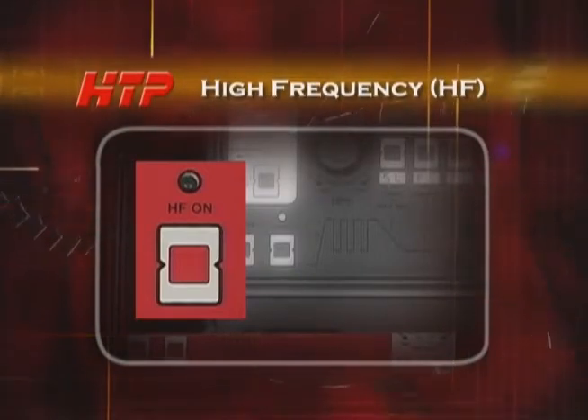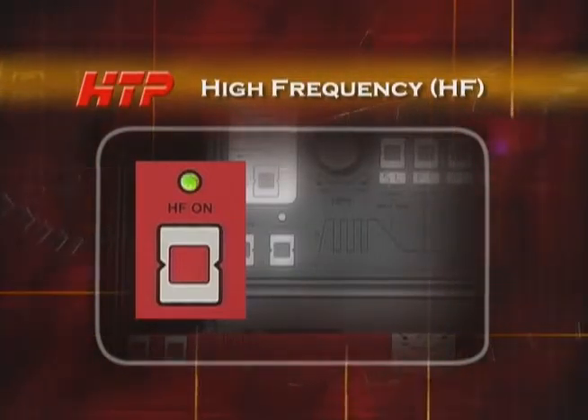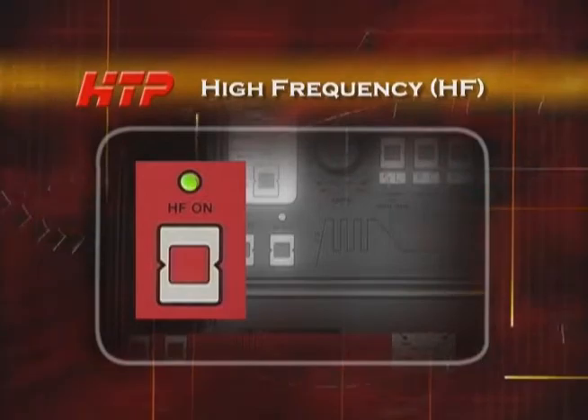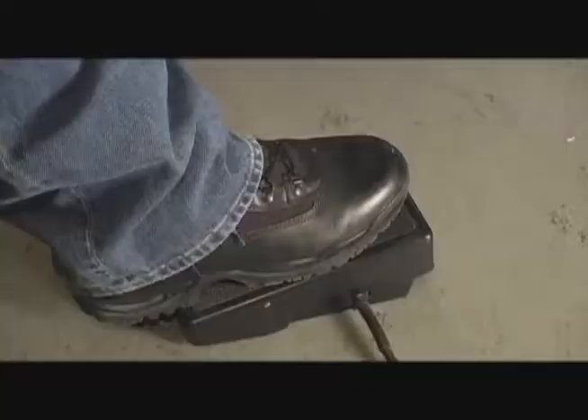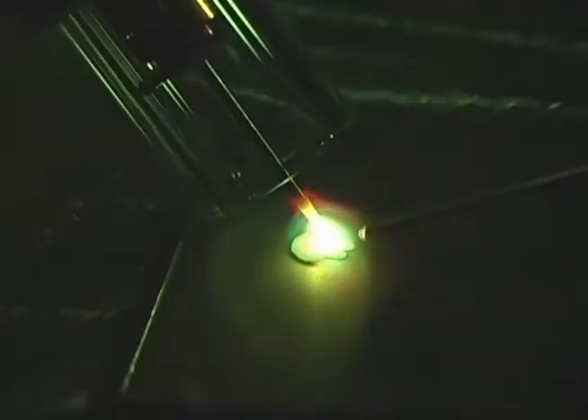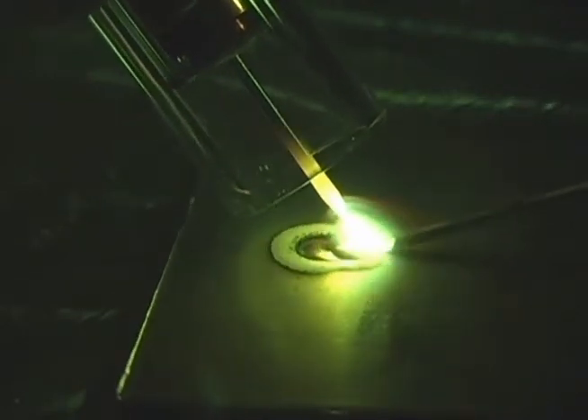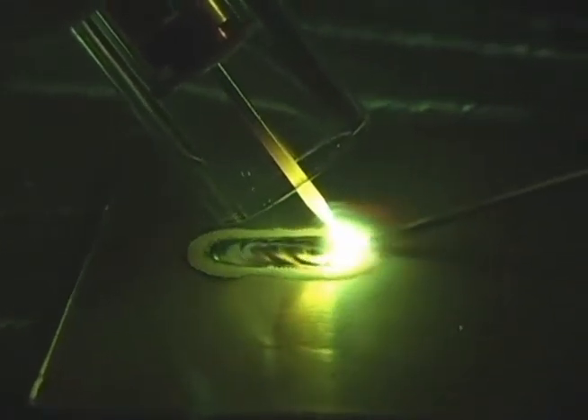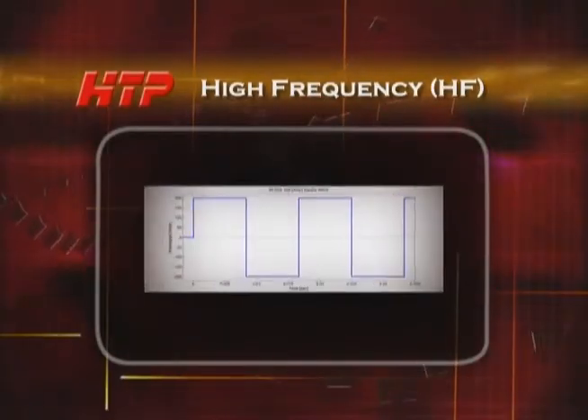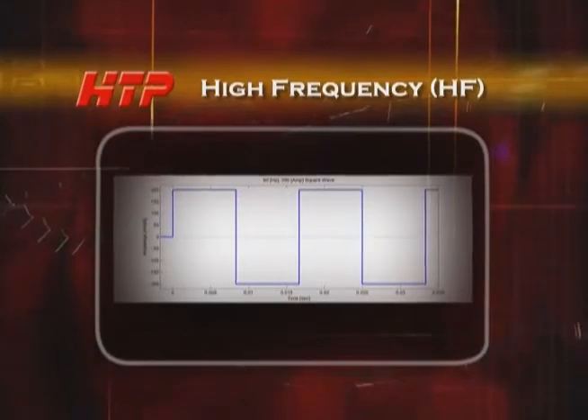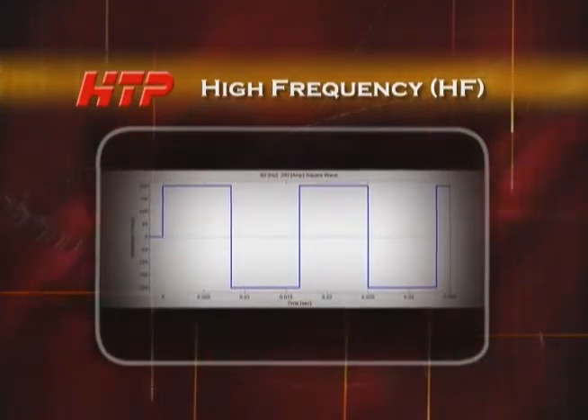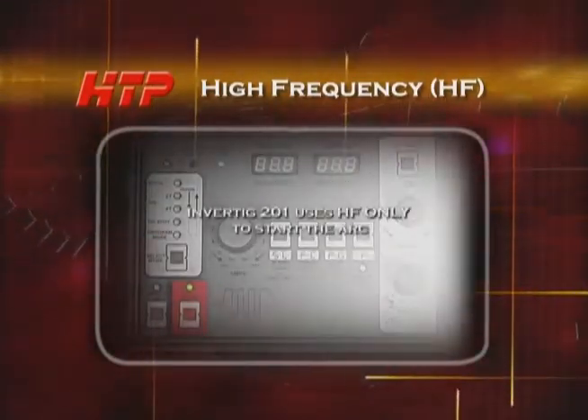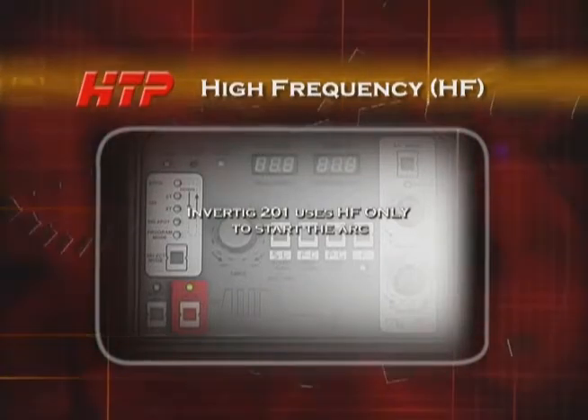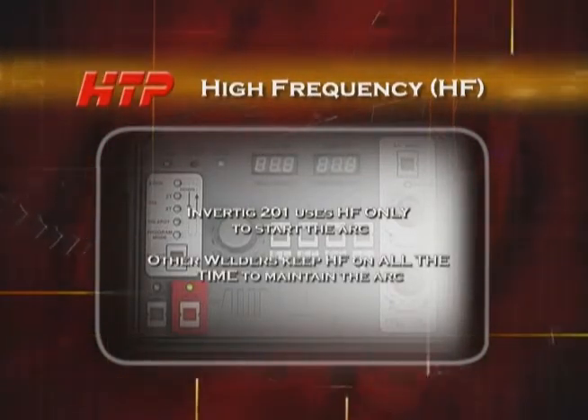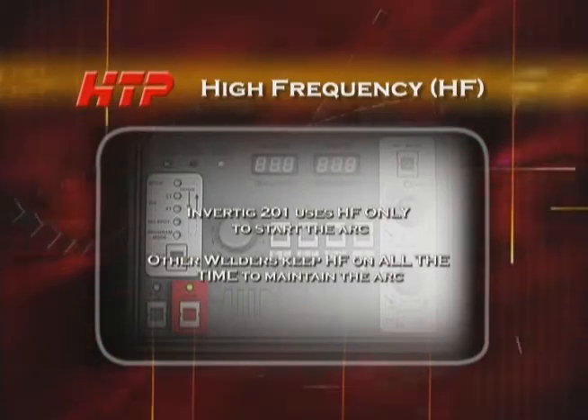Depressing the HF on button so the green light is illuminated turns the high frequency arc starting on. When the foot pedal is depressed, a high frequency arc will jump from the tungsten to the ground, initiating the arc. This makes it very easy to start the arc. Additionally, since the wave of the Invertig 201 travels so fast through the 0 point in the AC mode, the high frequency is used only to start the arc. Conventional transformer welders must have the high frequency on all the time to maintain the arc, which can cause interference.